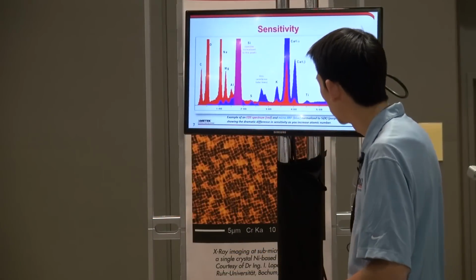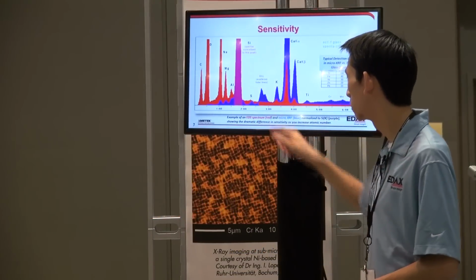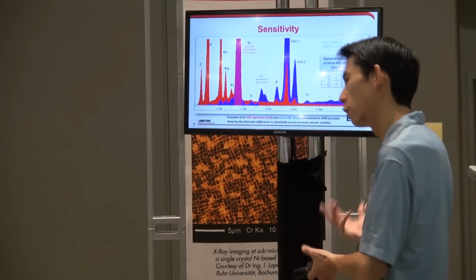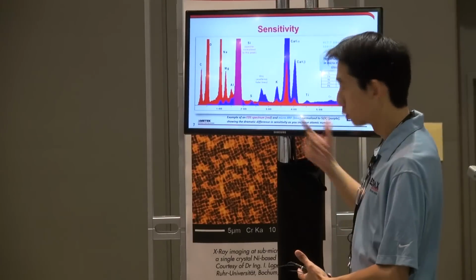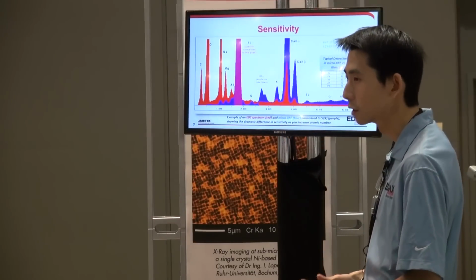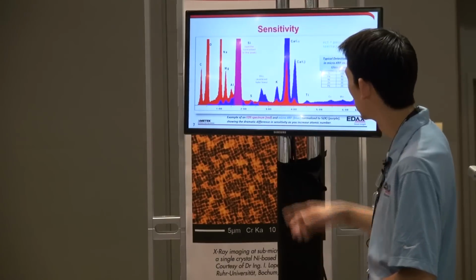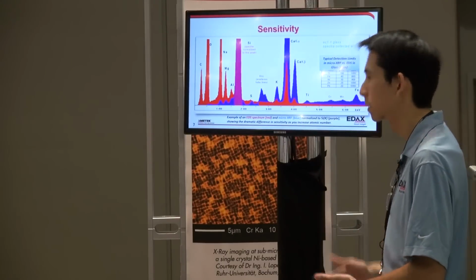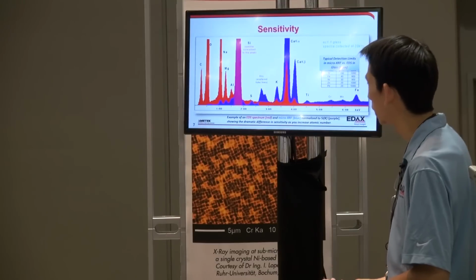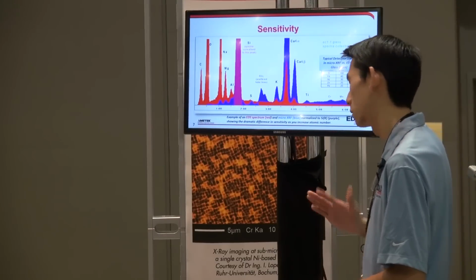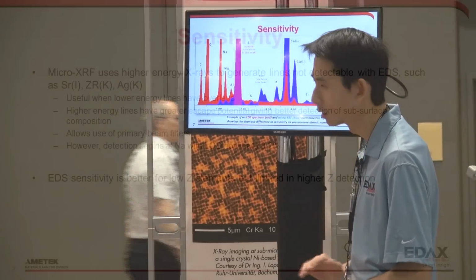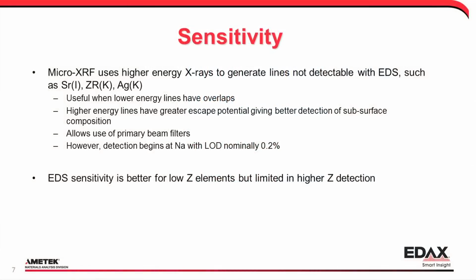One thing about XRF is you do pick up the tube scatter lines, so whatever anode material your tube has, you will get that line in your spectrum generally if you don't filter that out. So in this case we had a rhodium tube, and that's going to be an artifact peak that you see in your resultant spectrum. So that's one thing you don't have to deal with on the EDS side.